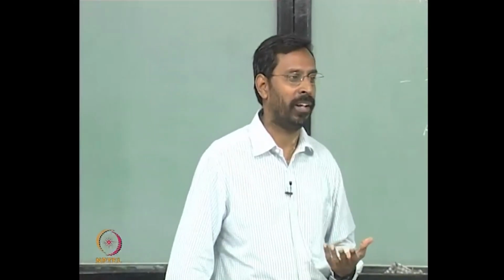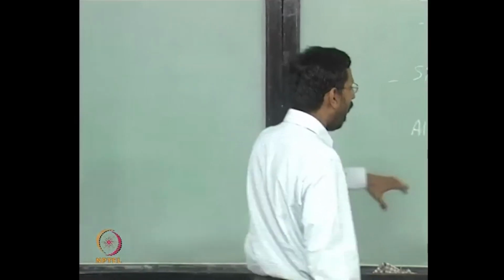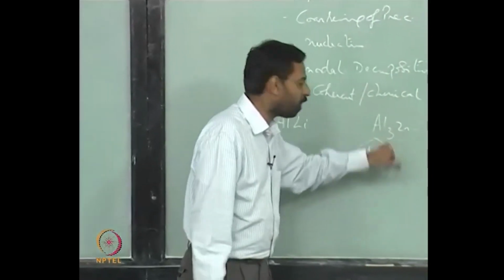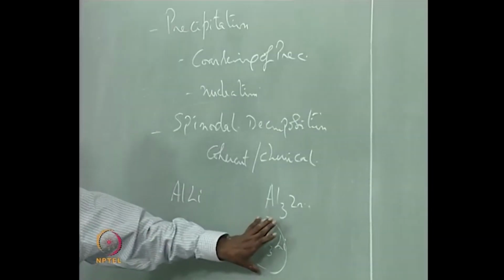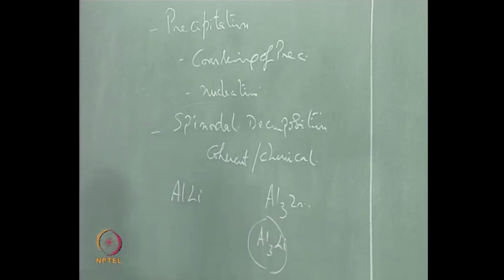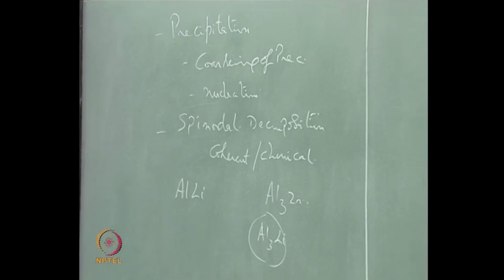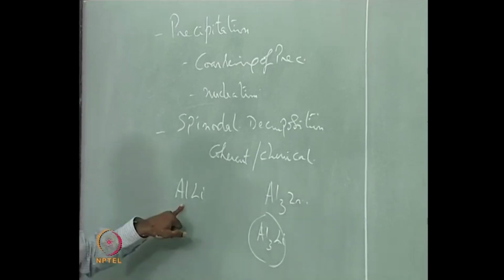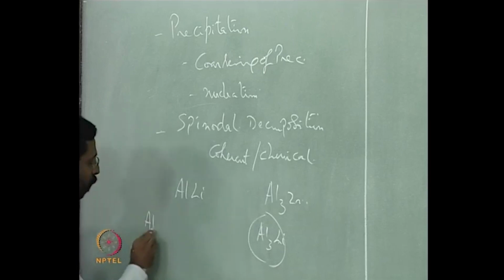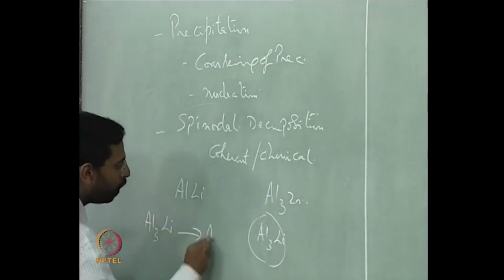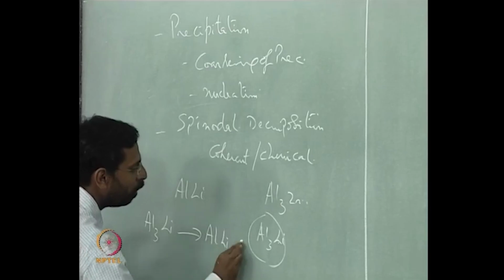when it solidifies ultimately. So what I mean to say is, when you look at structures like this, the fact that Al3Li is a metastable phase indicates that this ordered structure, if you heat it to higher temperature, Al3Li vanishes and finally gives you the AlLi. That means Al3Li in principle would split into AlLi plus aluminum.